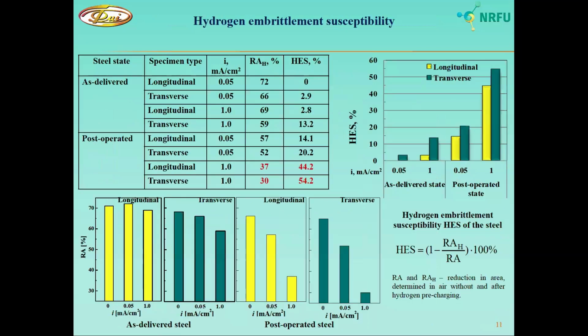Here we can see how hydrogen influences the reduction in area for the studied steels, and the lowest values were observed for the operated metal. And hydrogen embrittlement susceptibility for these steels was estimated by changes in reduction in area due to preliminary hydrogen charging.